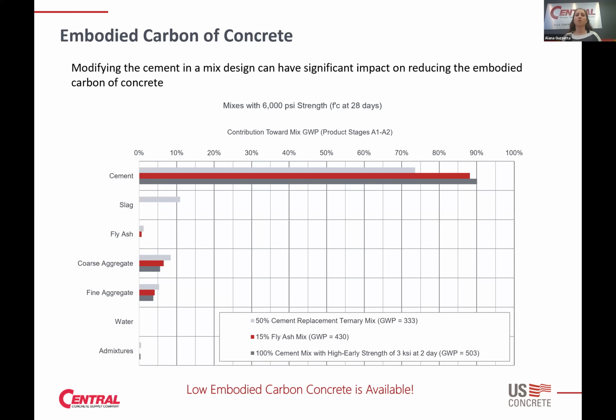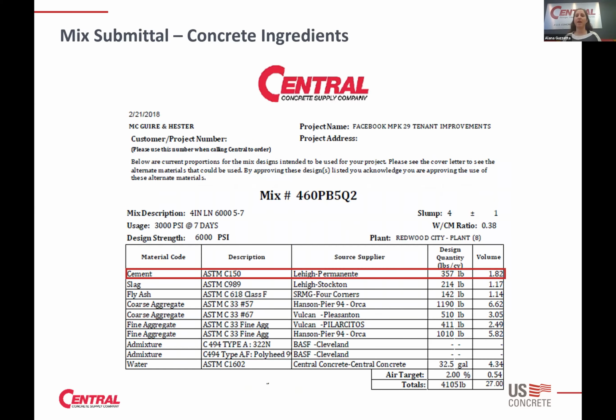And so you'll see that with the 100% cement mix, where cement is your only powder, in this specific mix example, 90% of the GWP for that mix design comes from the cement. And then you can see as you start replacing that cement, it becomes lower. And so you're anywhere from about 70 to 90% of the embodied carbon in the mix is coming from the cement. And so if we take then a first look at cement, what are our options then for reducing the embodied carbon of the mix?